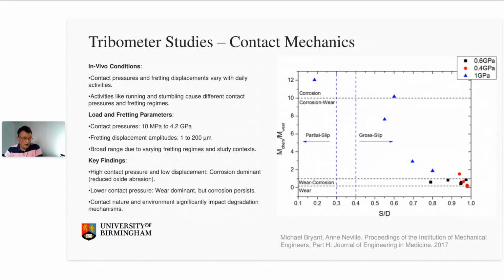So as we've heard from a number of the presenters already, fretting contacts and their input conditions can greatly affect the material degradation mechanism. A similar story is true for fretting corrosion contacts, and we've shown for cobalt chrome self-mated contacts that corrosion tends to dominate at relatively high contact pressures and at low displacements due to limited slip and exposure of that native, reacted underlying surface.